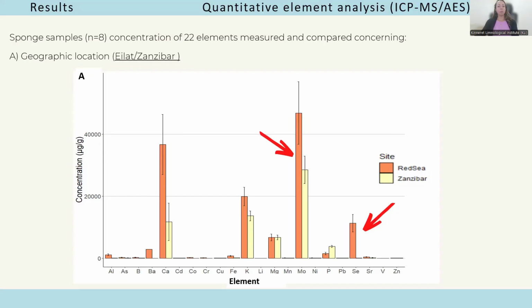in sponge samples from two geographic regions, the Red Sea and Zanzibar. The most striking result was molybdenum. In the Red Sea samples, molybdenum reached an average concentration of about 46,000 micrograms per gram dry weight. And Zanzibar samples also showed high concentration of about 28,000. Despite the geographic distance, the high molybdenum signal appears in both regions. This suggests that molybdenum enrichment is likely a species-associated trait, rather than a local contamination effect.